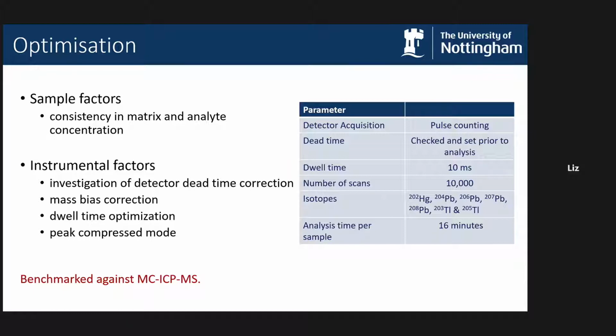And then we also did an external correction using the NIST standard reference material 981, whereby we ran that solution every 10th sample to allow us to do a linear correction by interpolation between those two values across the intervening samples.